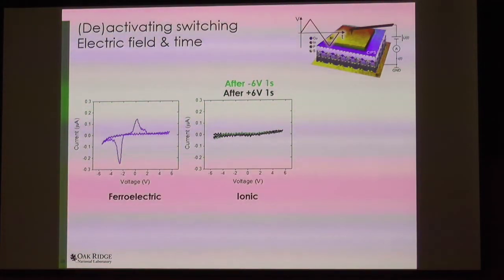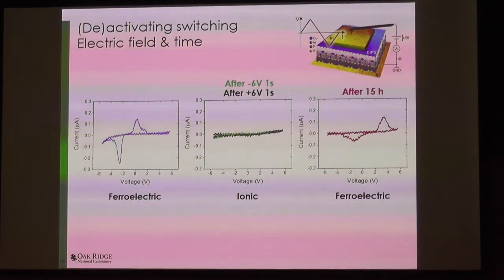this was not the case for this experiment. It was a different capacitor. The probe is much smaller, and the crystal was much thinner, just tens of nanometers. So I let the system sit for a while, and then did the same experiment again. And suddenly, all by itself, switching was back, and I saw nice switching peaks.